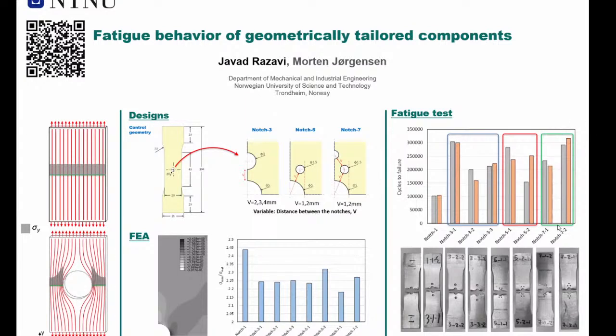One thing that we observed was that when the notches were closer, in the case of notch 5 and notch 7, closer to the main notch, the stress was showing to be quite smaller. But that caused an issue for us, that the crack after initiating from the main notch was approaching the adjacent notch. And eventually that resulted in lower fatigue life than what we expected. So overall, by keeping the distance in a reasonable place, we could get even a little bit higher than 3 times the fatigue life that we got.